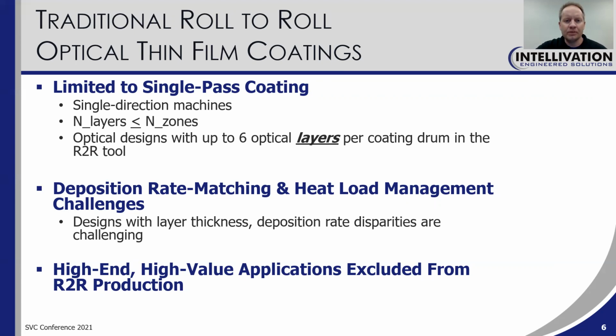And so some of the challenges that occur here are deposition rate matching, for example, and heat load management. So if you have a recipe that calls for a very thick material that's a low deposition rate material, and then a very thin material in general, or a thin high rate material, that creates some challenges in producing that coating. And so for these reasons and others, some of the high-end, high-value applications were excluded from roll-to-roll production.